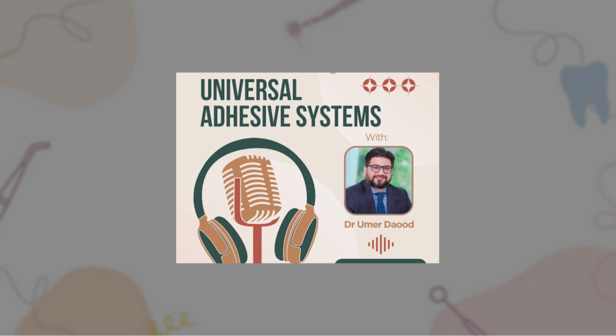All right, thank you for that question. The perspective is very positive regarding the universal bonding system because it's not moisture sensitive, so you can use it on wet, dry or moist tooth structure, because it's bonding to all the substrates. And you can use it with all direct and indirect restorations, probably more than 10 micron thickness. And it has an ideal chemical balance for both total etch and self-etch adhesion, from one bottle as we talk about it.